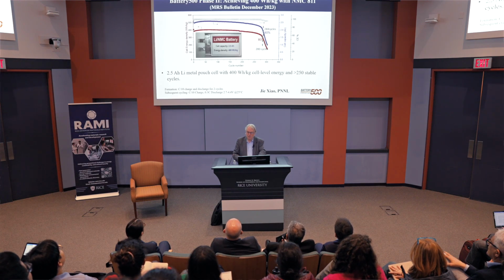And I should emphasize, these are all what we call pouch cells. You see a little cell here. The energy densities here are real. You may say, what do you mean by that? We weigh the cell, so it's everything in the cell. If you read the literature and somebody will say, we've got 600, 500, 400, look at the fine print. It'll either be active material or it'll be when extrapolated to a cell that's 10 times bigger than what we've got today. And this is a particular case with startup companies and some large corporations. So 90% of what you read in the literature is hype. So be very, very careful what's out there.